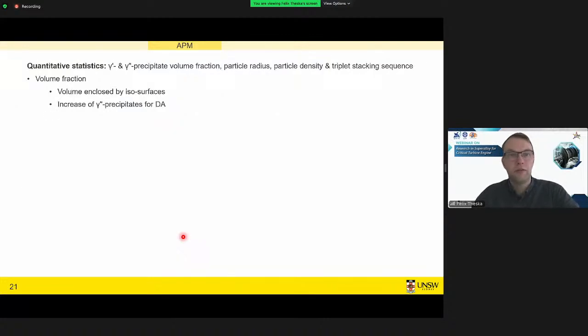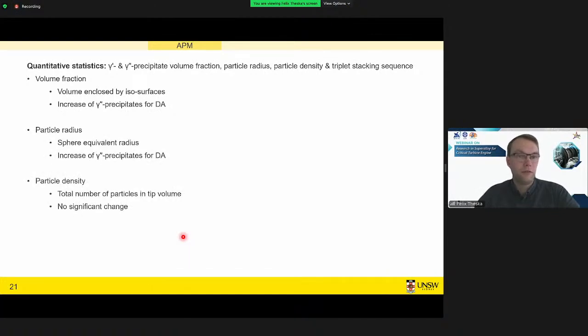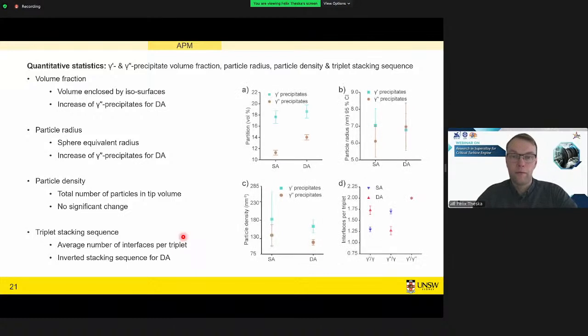But we can also extract all other sorts of information from these particles, such as volume fraction, the particle radius, particle density, and even the triplet stacking sequence we can quantify. So for example, if we look at the volume fraction on figure A, we do see there's significantly more gamma double prime after direct aging. The gamma double prime particles are also larger. The particle density has not really changed that much. But if we focus only on the triplets, we do find this inverted stacking sequence just by looking at the interfaces.